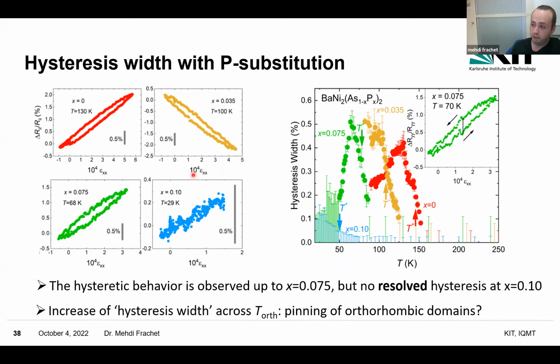But in the undoped compound, I think I can reach kind of the same conclusion. In the undoped compound, we see the same thing: the hysteresis onsets with the increase of the intensity of the incommensurate charge wave. Now in the doped phosphorus compound, I see a finite hysteresis that develops when the intensity of the incommensurate charge wave is already substantial. But this quantity is not super easy to extract, and to observe a finite hysteresis, it needs to be above the experimental noise, which depends on the sample. So that's difficult to make a conclusion.